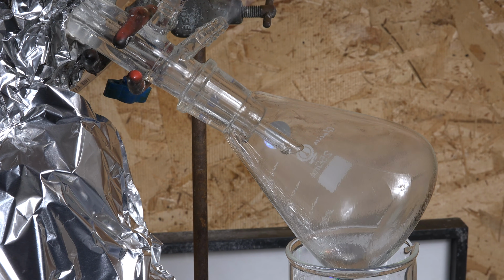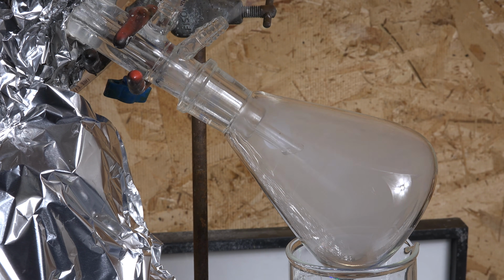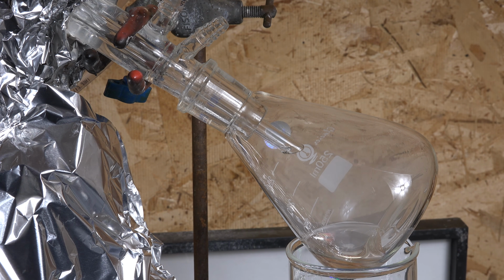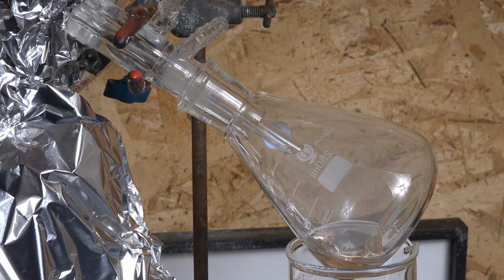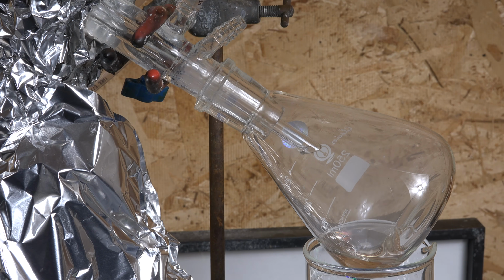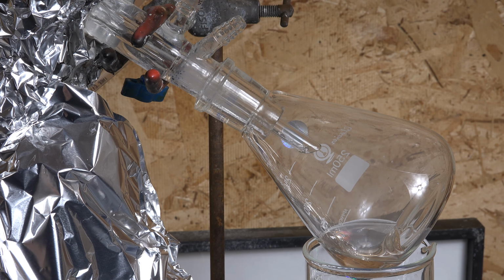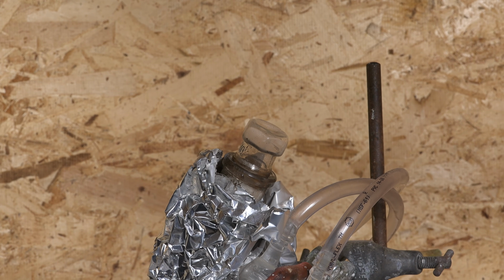I did another trial, but instead of gently raising the temperature during distillation, I tried blasting through it on full heating. But it seems temperature control is much more important than usual. If heated too high too fast, we get severely reduced yield. I think at high temperature, the sodium bisulfate produced itself starts to pyrolyze and release water, reducing yield. So maybe the insulation and higher temperature during the pyrolysis step isn't what's increasing the yield, but the insulation allows me to be very precise and gentle with the heating in the distillation step. I'm not exactly sure, that's just a hypothesis. This could simply be a bad run. We'll need a lot more testing, and that's why I'm making these lab notes.